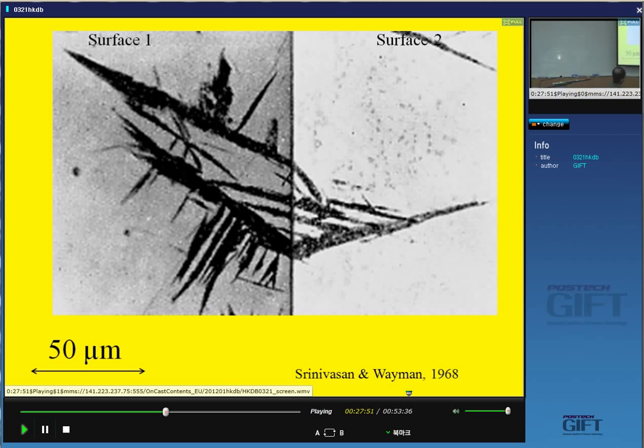Carbides. Yeah. So this is untempered martensite, so there aren't many interfaces to attack with a chemical. But this contains structure in the form of carbides and so on. Therefore, an etchant will attack it more, and you can recognize optically the difference between bainite and martensite if you have both of them in your structure. Obviously, if it's fully transformed, you can't tell the difference optically, but you can see the contrast is pretty spectacular.